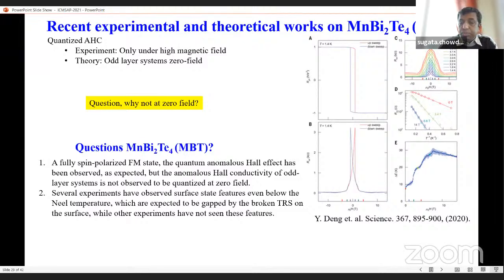There are two different questions we focus on. It is a fully spin polarized ferromagnetic state. The quantum anomalous Hall effect has been observed as expected, but the anomalous Hall conductivity in the odd layer system was not observed to be quantized at zero field, and why is it so? And several experimental groups observed surface features even below the Néel temperature, which is expected to be gapped due to the broken time-reversal symmetry.